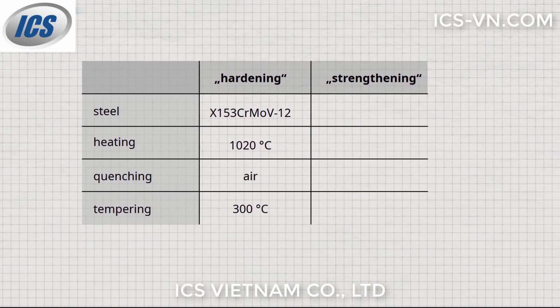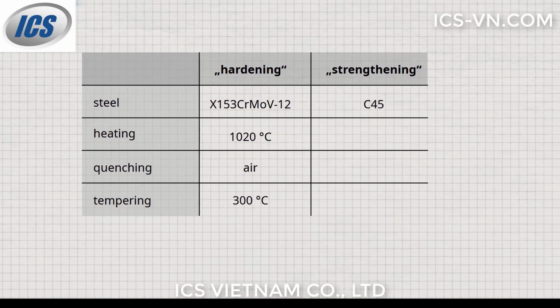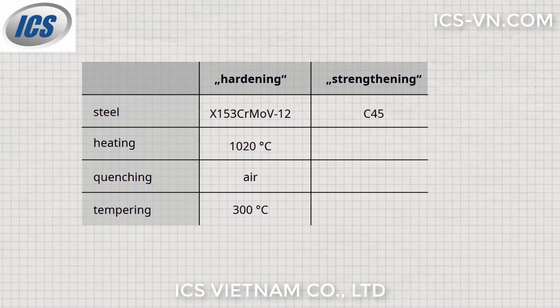As a second example, an unalloyed steel with 0.45% carbon is considered for quenching and tempering. In this case, the austenitization temperature is around 840 degrees Celsius.